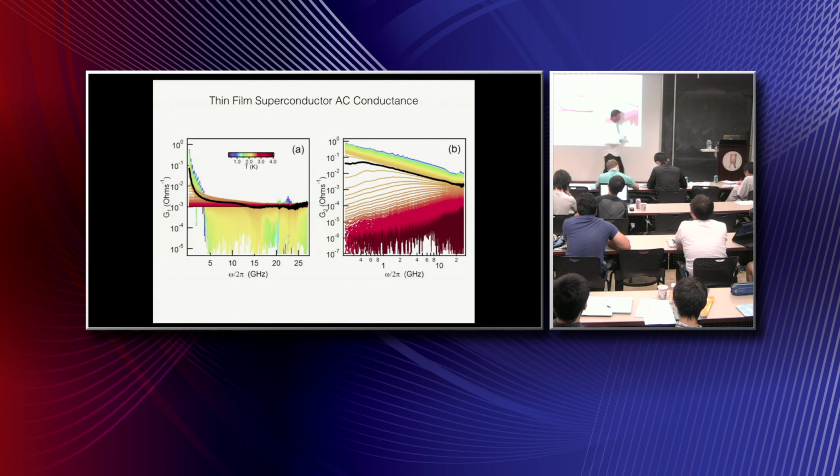We're going to talk about superconductors in different contexts, but the thing I want to concentrate on is first at high temperatures, which in this case is 3 degrees Kelvin, meaning the normal state. This flat line that's buried under here, that's the normal state. This film is a disordered superconductor. If you were to ask what its normal state scattering rate of the electrons is, it's let's say 100 terahertz. So it's super disordered, something very, very large.